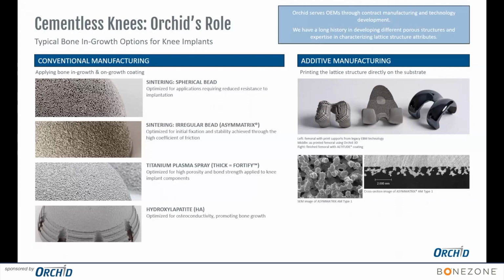And then over time, it has become well established that that particular surface is relatively smooth, and early fixation, as Trey had mentioned, is very, very important. So a rough surface, which has a higher coefficient of friction against bone, became an important consideration as the sintered porous coatings developed with time, right? So we have what is known as irregular coatings. And the difference between irregular and spherical beads is literally just the shape of the powder that is utilized in the sintering process, right? So the spherical beads essentially give you a conformal surface in the boundary itself, while the ASYMMATRIX coating or the rough coatings essentially have a lot of spicules that stick out of the surface itself that give you the additional coefficient of friction.